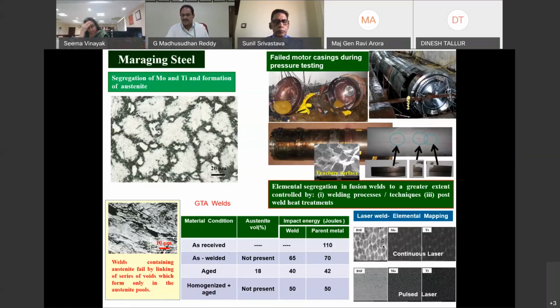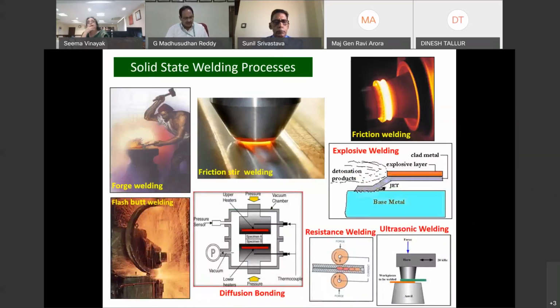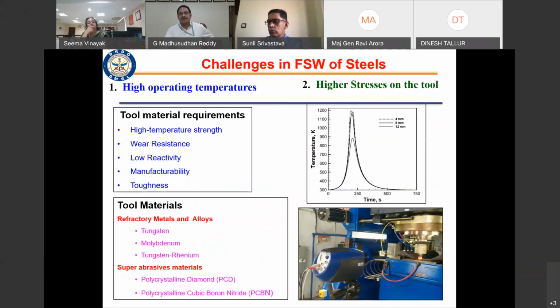So how to enhance the fracture toughness? The best thing is, why can't you look for a process in which there's no melting at all? These are some of the solid state welding processes, and there are several challenges in using this process for welding maraging steels. I'm showing an example of friction stir welding. It is a non-fusion process, and there are several challenges because when you're trying to weld it, you need a tool.